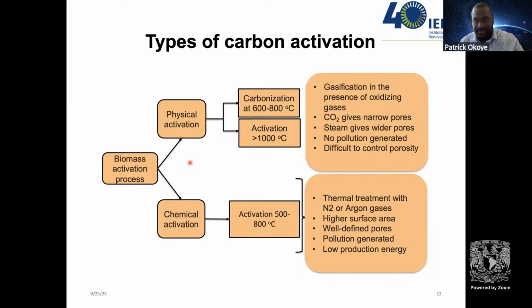In essence, physical activation is a two-step process where we do carbonization. The term carbonization is controlled temperature treatment at some elevated temperature between 600 to 800 degrees Celsius, and then activation in some oxidizing atmosphere. So for physical activation, you have some oxidizing gases like CO2 or steam. One of the challenges with physical activation is that either you are using CO2, you have narrow pores, or you are using steam, you have much wider pores.